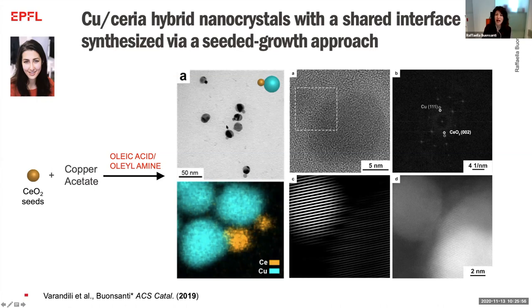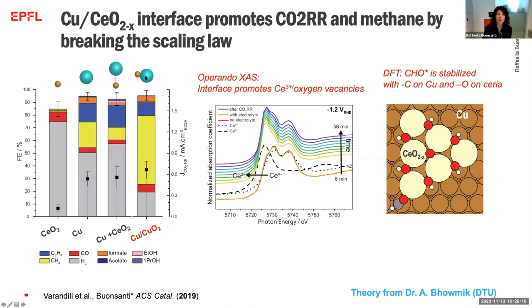The way in which she synthesized them is by what we refer to as seeded growth. So basically, she has in her flask some ceria seeds, and then she heterogeneously nucleates the copper in the presence of some ligands. And these ligands, I will show you later, are crucial for these catalysts to form. So what Denaz found is that when she compared these heterodimers with the mixture of the two domains separately, she did indeed observe that the hydrogen is tremendously suppressed and that the CO2 reduction reaction is promoted. And among all the different products, this is methane. So the methane is dramatically enhanced.